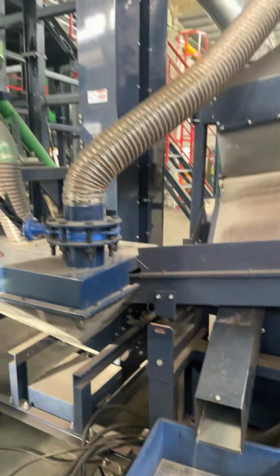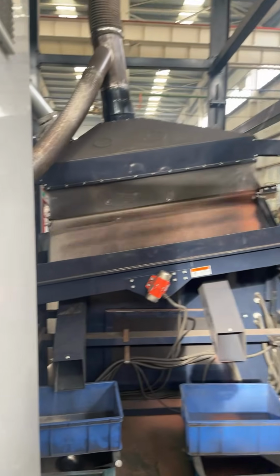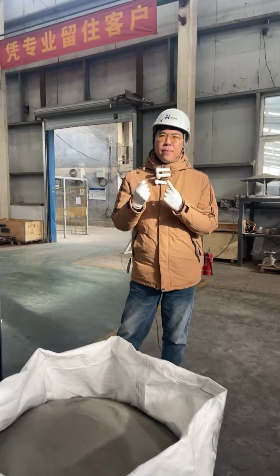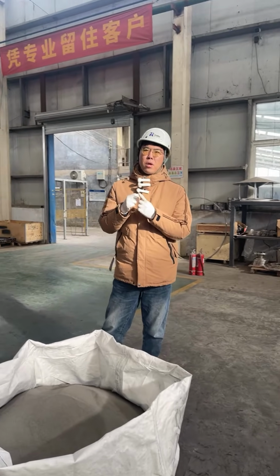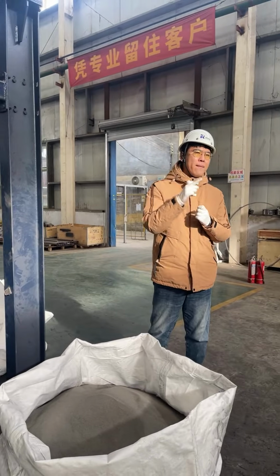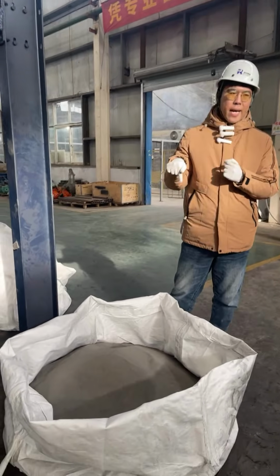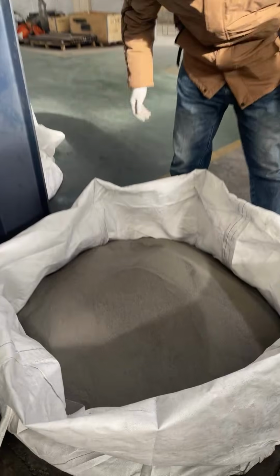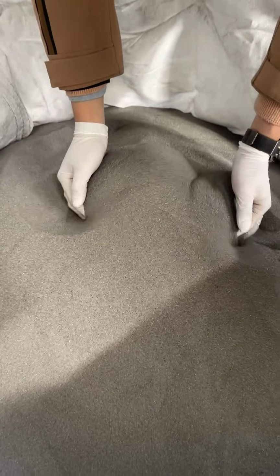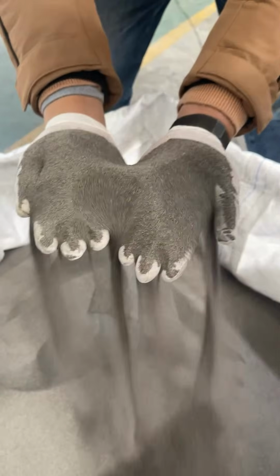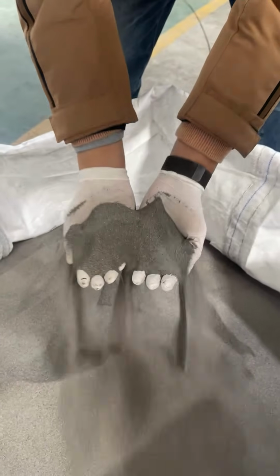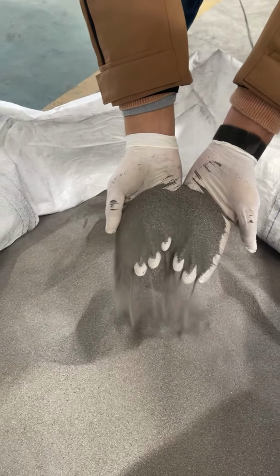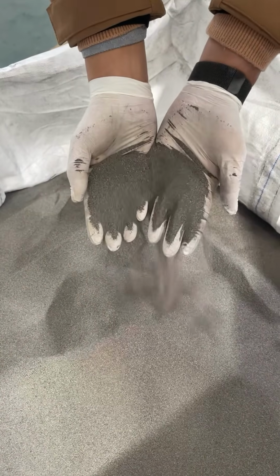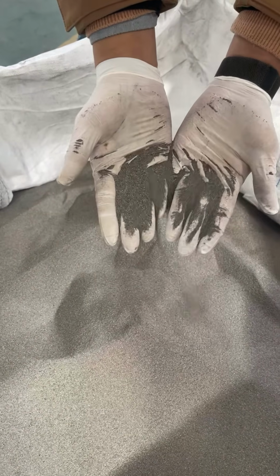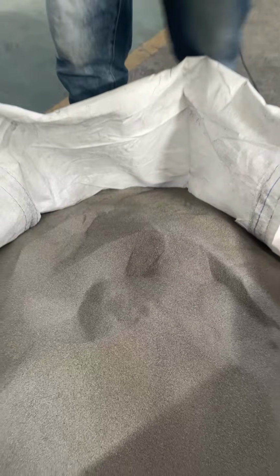Because we have run the system for 2 days, we have processed about 10 tons of material. And from 10 tons of battery, you can get about 1 ton aluminum and 1 ton copper, which we can see from the big bag. This is what we got from the day before yesterday, and today morning. Those are the aluminum we got. I have to admit that this is the most pure aluminum I have ever seen in those years. And another bag we can see.